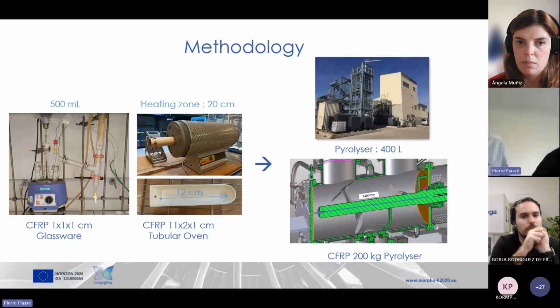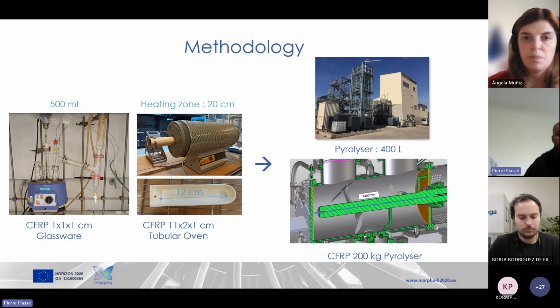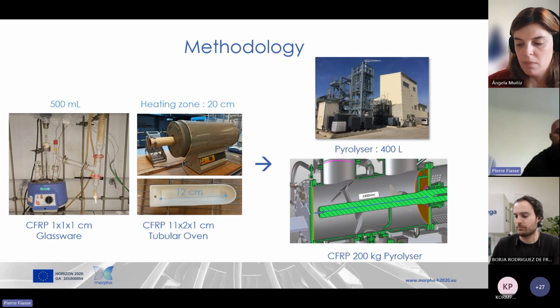Okay, hi everyone. As it was explained on the previous slide, the method consists of first performing several tests on lab scale and tests just after for the upscaling. We use two different types of reactor on the lab scale. You can see on the left side the glassware reactor and on the right side the tubular oven. The advantage of the glassware is that we have good flexibility to modify and adjust the parameters, like temperature. You can put a probe in different places. You can also look at the temperature of the vapor, of the liquid, and you can easily adjust the temperature of the test if you want.